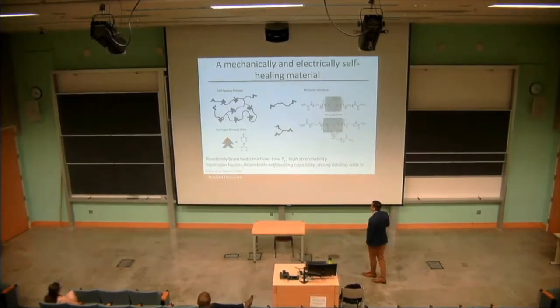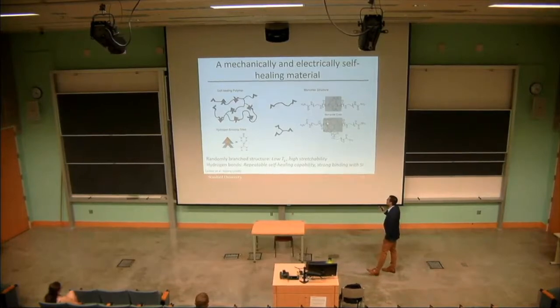So we chose a self-healing hydrogen bonding polymer. It is basically these dimer and trimer structures that self-associate via urea bonds into this polymer network. It has a non-polar core that gives us a very low glass transition temperature, which allows for dynamic motion of these hydrogen bonds at room temperature. So we get fully autonomous self-healing at 25 C.